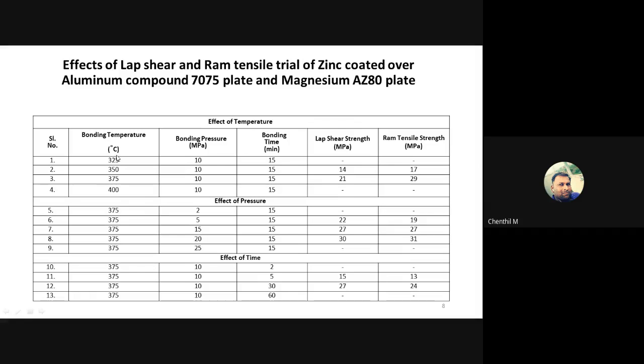So as in the first 1, 2, 3, and 4, we can see that we are varying the temperature from 325 to 400 degrees Celsius. Here we have kept the pressure at 10 megapascal as a constant and bonding time as a constant. Whereas for 325 we have not achieved a bonding structure, so it was considered that we have to increase the temperature.